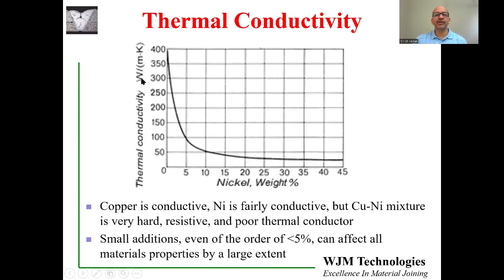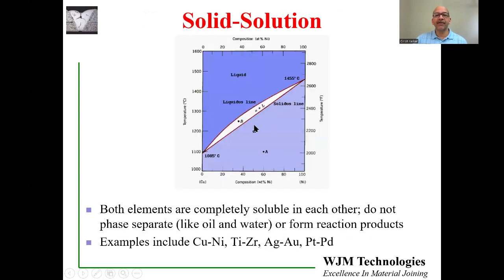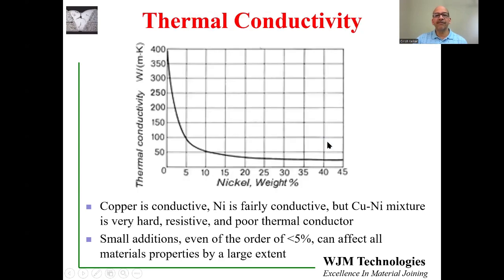So on this chart, I'm showing you thermal conductivity of a mixture of copper and nickel. And on the left axis, we have pure copper. As we increase the amount of nickel, you will see that the conductivity, thermal conductivity in this case, drops very quickly, even with 5% nickel in copper. So the properties of copper nickel are not linear. So even though the diagram looks pretty simple and straightforward, the material properties of the mixture are not linear. So even a small fraction of nickel can significantly affect the behavior of the mixture.